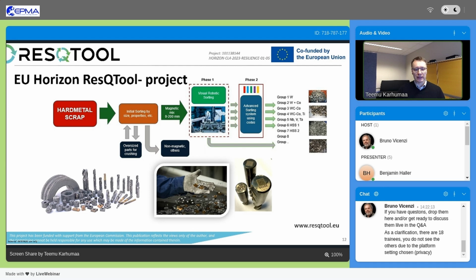They consist of different elements, not only tungsten carbide and cobalt, but there are differences in tungsten carbide grain size, and there are other elements sometimes. So our current idea in the ResQTool project is to create a standard in Europe, and hopefully expand it even further, that the hard metals would contain a data matrix code, and the code would contain information on what the tungsten carbide grain size is and what the chemical composition of this hard metal tool is, so that it could be recycled as easily as possible without losing any critical raw materials.